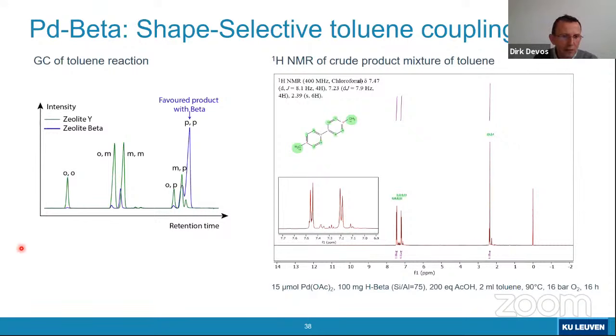To just convince you that these effects are pretty drastic and surprising, here is even a very early chromatogram from many years ago in which we compare the product distribution of zeolite Y with that of zeolite beta. And then you see that indeed there is this very big peak of the para-para product that stands out with zeolite beta, whereas on zeolite Y and also in homogeneous catalysis, you would have a much more statistical distribution. The same idea comes out of the proton NMR that you see here. This is just a crude proton NMR of a reaction mixture. And then you see that even in the crude mixture, the spectrum in this aromatic domain is dominated by para-disubstituted arenes. So each of these rings is now para-disubstituted, and that gives you this typical pattern that all of you know very well from your basic organic identification classes.